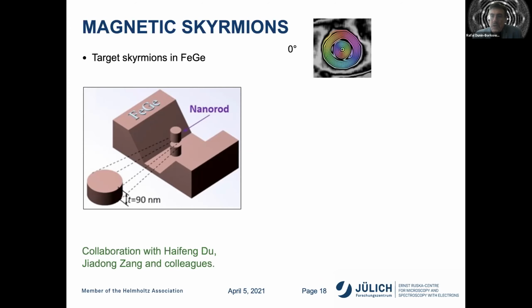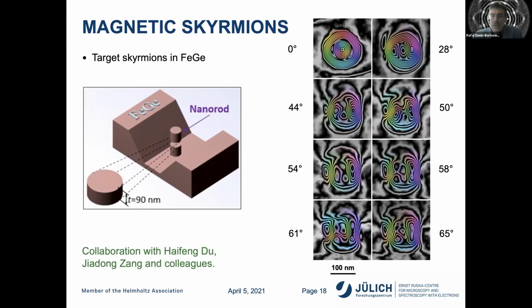The complexity, though, becomes apparent if we tilt this object about a horizontal axis. And I'm now going to show a tilt series of magnetic states. And these tilted magnetic states go down to about 60 degrees tilt about the horizontal axis. And whereas everything looks nice and symmetrical when you look along the cylinder along its axis, as it's tilted, you begin to see that magnetically the object is asymmetrical horizontally and it's asymmetrical vertically. In fact, it probably has a mixed Bloch type and Néel type character, which we would like to image in 3 dimensions, but that reconstruction hasn't been carried out yet.